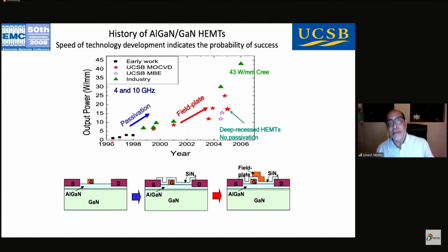We at UCSB, at UC Santa Barbara, showed the first microwave power performance of an AlGaN/GaN HEMT in 1996. And it went from 1 watt per millimeter to 4 watts per millimeter. Then we introduced silicon nitride passivation, not only us, Santa Barbara, Cornell, Cree at that time. That passivation got the power up to 10 watts per millimeter. Then at UC Santa Barbara, we introduced the concept of a field plate, which basically spreads the electric field. And that got us from here to 25 watts per millimeter. And then at Cree, by using multiple field plates, we ended up showing 43 watts per millimeter.